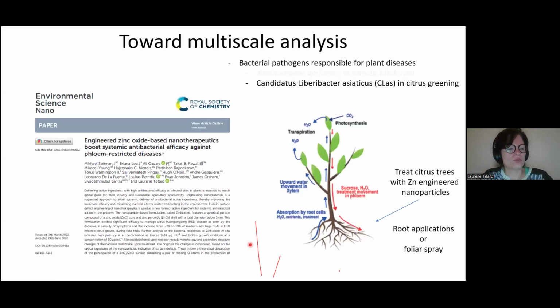So lastly, I want to show this example of the study we did on zinc oxide-based nanotherapeutics. That was part of the CLAS project, and that was a multi-year, multi-investigator project to get to this publication. At the time, Dr. Santra was developing this zinc oxide nanoparticle that has a shell of zinc peroxide, and that was very small. The diameter of individual nanoparticles was below 5 nanometers.